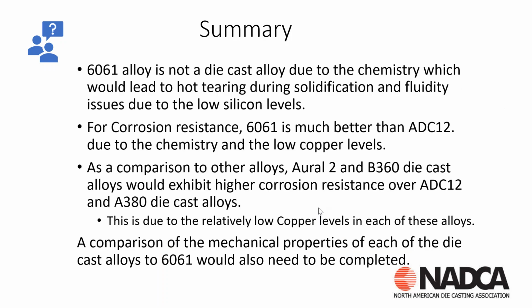So as a quick summary, 6061 is not a die cast alloy due to its chemistry. That type of chemistry is going to lead to hot tearing during solidification and have some fluidity issues due to those low silicon levels. For corrosion resistance, 6061 is much better than ADC 12 due to the chemistry and those low copper levels. Now, as a comparison to the other alloys, Aural 2, B360, those are going to have better corrosion resistance over ADC 12 and 380. Once again, due to that low copper level.